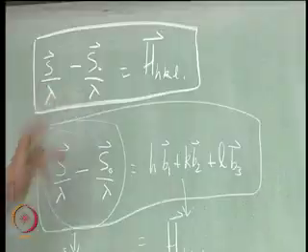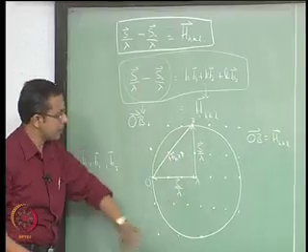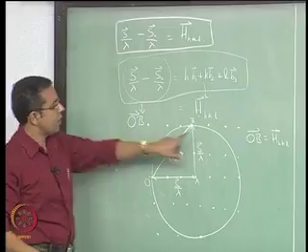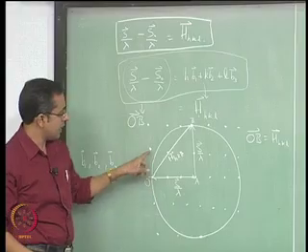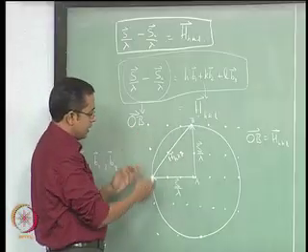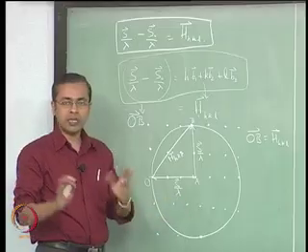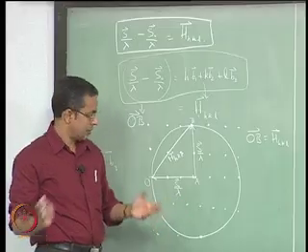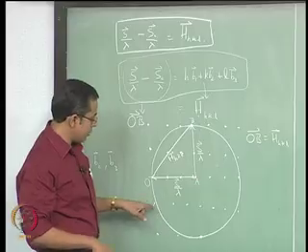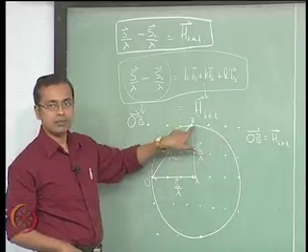This equation is satisfied, I have plotted this in a 2-dimensional sense. So in this 2-dimensional figure this equation is satisfied whenever this circle touches any of these points. As you can see clearly there are several points here which are not being touched by the circle, therefore with respect to those points diffraction is not going to occur, that is number 1. And number 2, there are several regions of the circle which are not touching any point, okay.